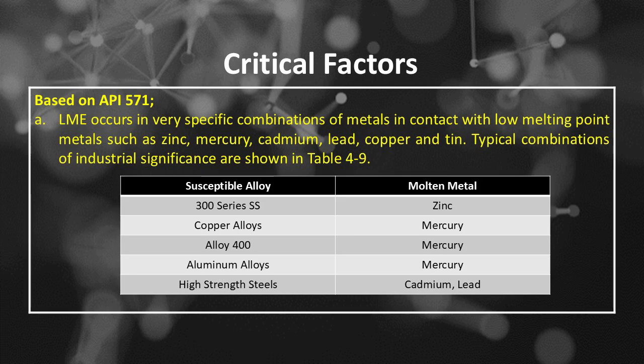Critical factors based on API 571, number A: LME occurs in very specific combinations of metals in contact with low melting point metals such as zinc, mercury, cadmium, lead, copper and tin. Typical combinations of industrial significance are shown in Table 4.9: 300 series SS susceptible to LME when combined with zinc as molten metal, copper alloys susceptible to LME when combined with mercury as molten metal, alloy 400 susceptible to LME when combined with mercury as molten metal.